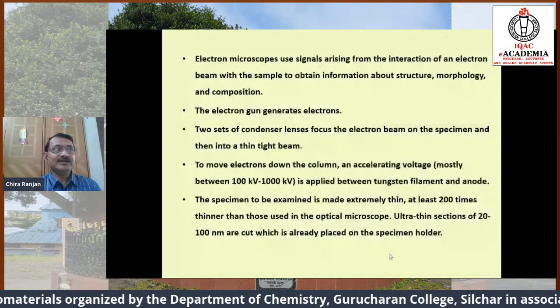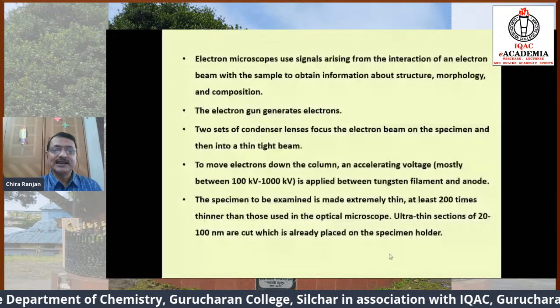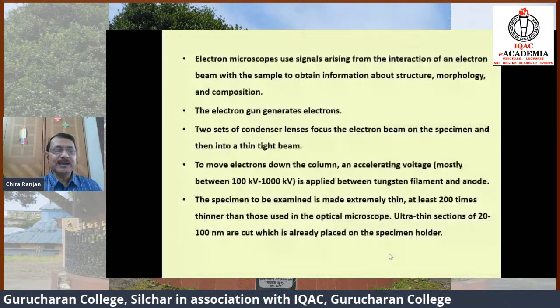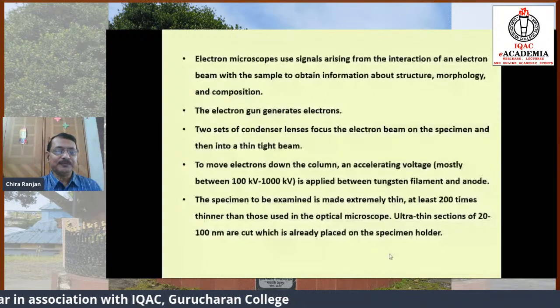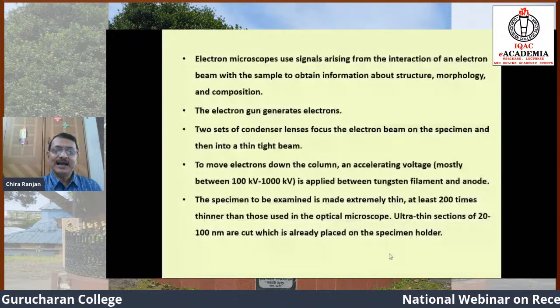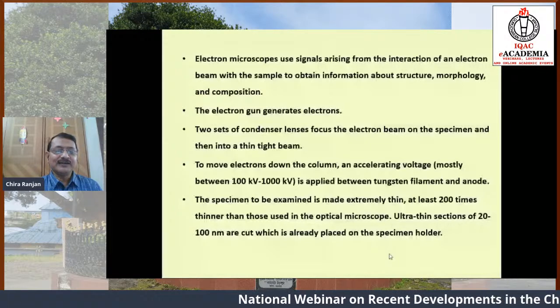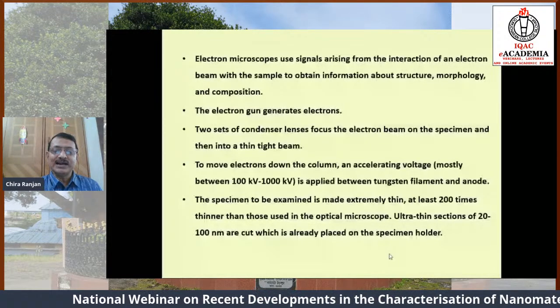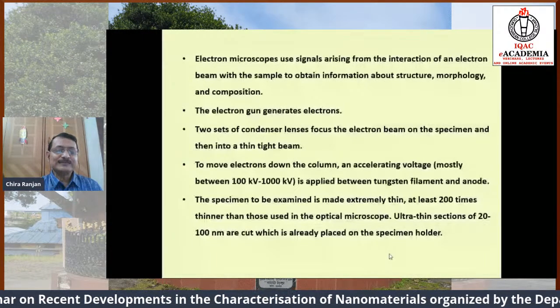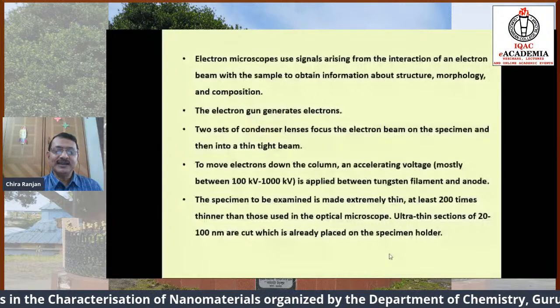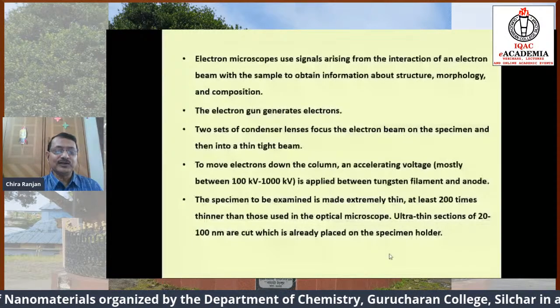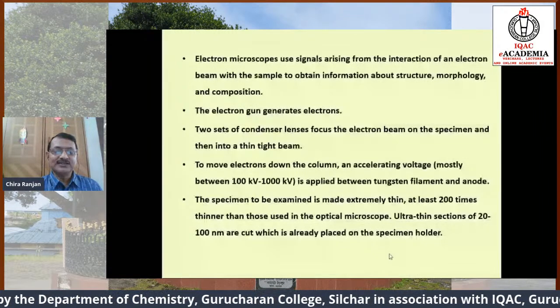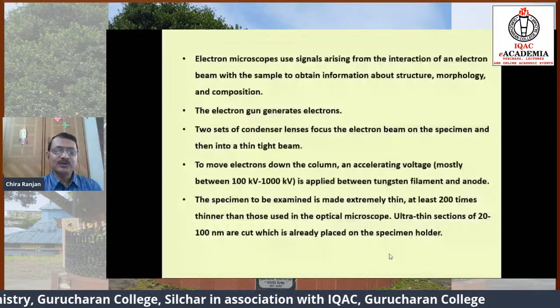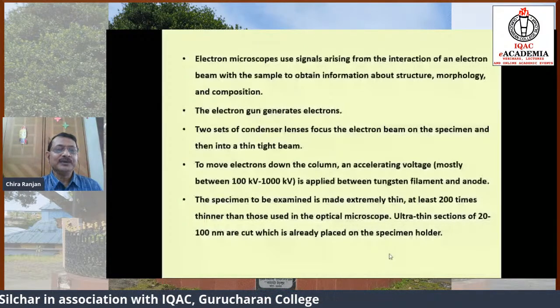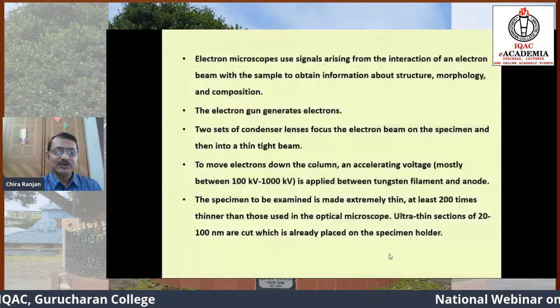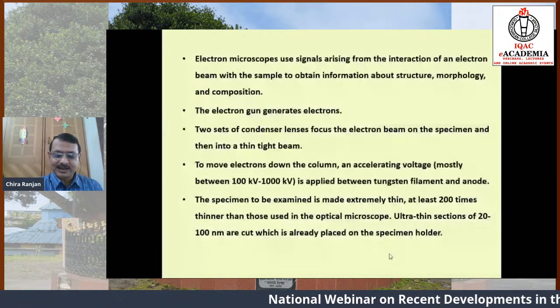The electron gun generates electrons. Two sets of condenser lenses focus the electron beam on the specimen and then into a thin, tight beam. To move electrons down the column, an accelerating voltage between 100 kV to 1000 kV is applied between the tungsten filament and anode. The specimen to be examined is made extremely thin, at least 200 times thinner than those used in the optical microscope. Ultra-thin sections of 20 to 100 nanometers are cut, which are placed on the specimen holder. So these are some of the instrumentation aspects, of which I will only give the salient features.